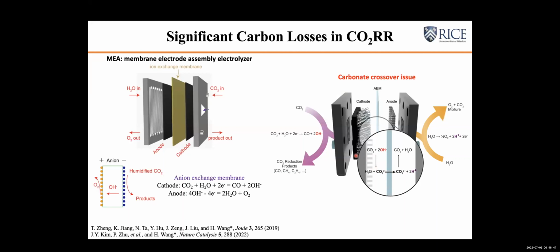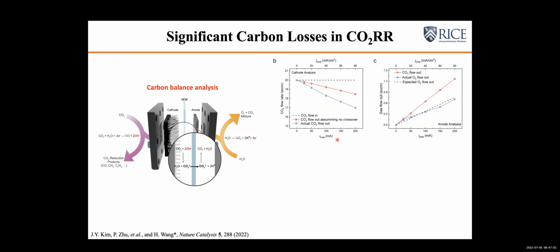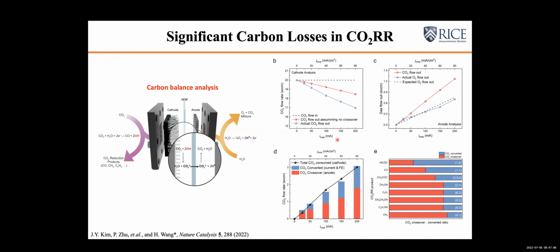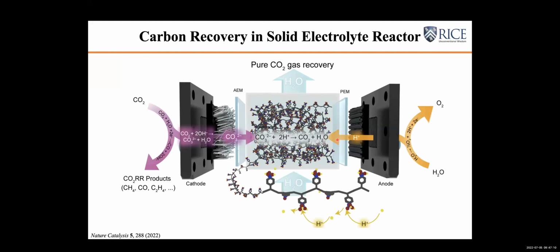But the challenging part is that it will come out together with oxygen, and if CO2 is mixed with oxygen, you cannot reuse it anymore, because you cannot directly refeed it back to the CO2 reactor. But you can do some downstream gas separation process. I don't have the time to go into the details of that, but one potential mitigation method is to have this solid electrolyte buffer layer, where you allow the carbonate to cross over, no problem, but block it from continuing to travel into the anode. So you have this solid electrolyte layer where the protons generated from the anode come to the middle layer to neutralize the crossover carbonate and generate high purity CO2 gas again. So that can be recycled back to your cathode for continuous utilization.